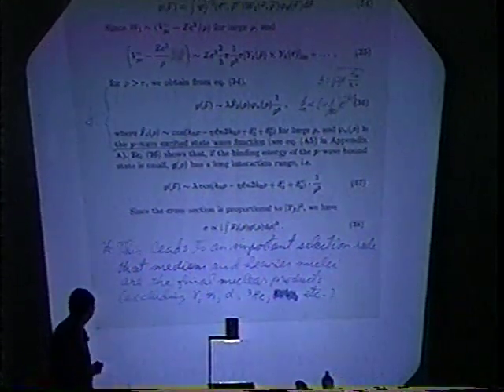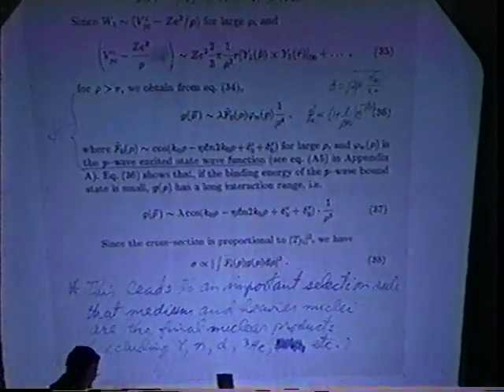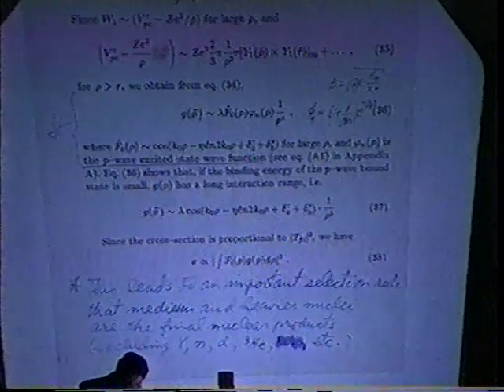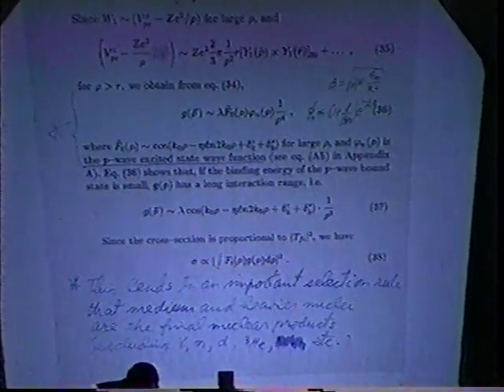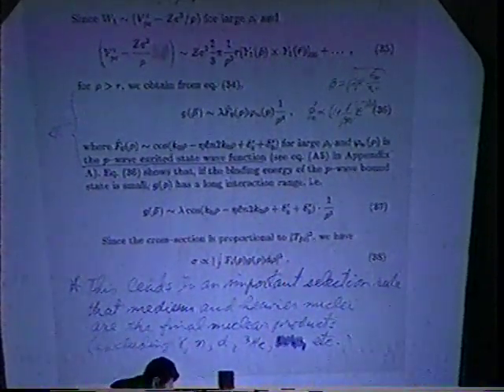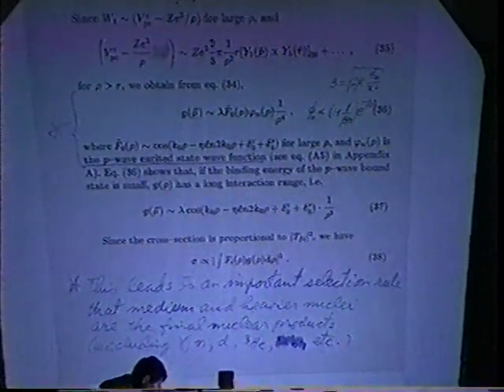It's an excited P-wave state. But this may have an important consequence, because not all of the nuclei, especially light nuclei like deuterium, helium-3, and neutron, obviously don't have a halo nuclear state. And this enhancement effect will not occur. If the final nuclei had the halo excited state, then enhancement can occur, which means you can rule out lots of lighter elements and the gamma rays and neutrons. But the medium and the heavier nuclei, which might have a halo excited state, will get an enormous enhancement of the cross-section, which may explain some of the transmutation results, but by no means completely.